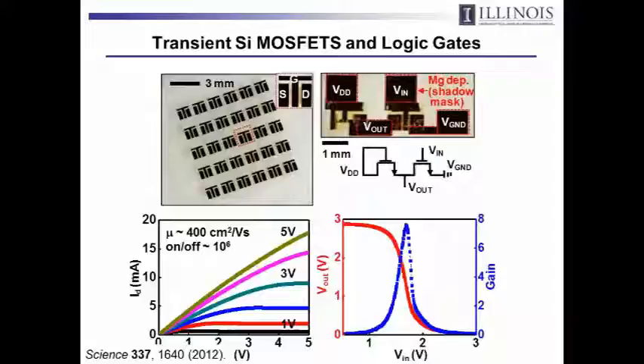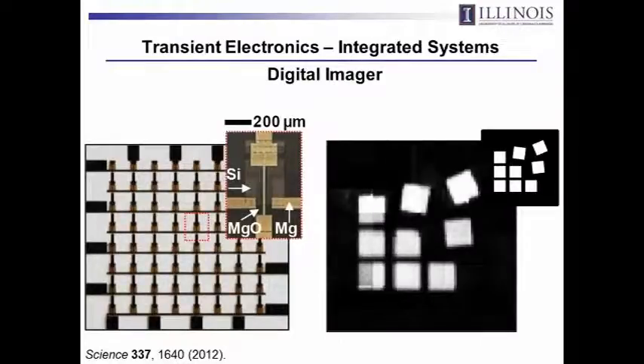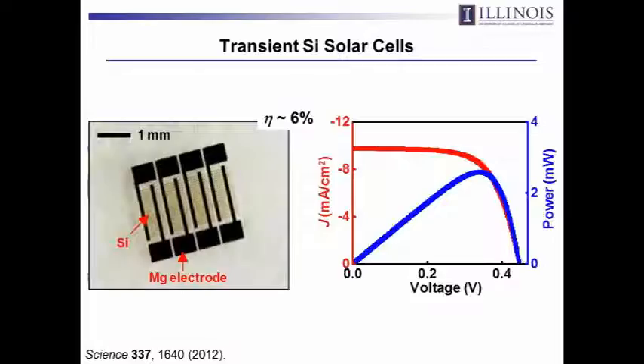As I mentioned, silicon is a well-known material. There are well-known device architectures. So almost immediately, you can go off and build all of the component building blocks that you might be interested in for an integrated circuit. Here's a transistor, with very good switching characteristics, a factor of 1,000 or 10,000 times better than what you can obtain with organic alternatives. You can make simple logic gates that behave in an expected way. You can also make photodetectors and diodes, and this is just an imaging array. It's an array of ultra-thin silicon photodetectors, and you can take pictures with that kind of image sensor, but at the same time it's made out of completely water-soluble materials.